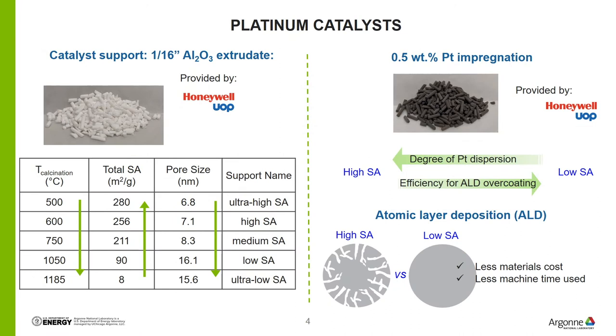This slide shows how the catalyst support looks like. The catalyst support here, which is used to support Pt nanoparticles, is a 1/16-inch diameter aluminum oxide extrudate. The same extrudates were calcined under 5 different temperatures to tune the surface area and pore size. From the table, we can see with the increase of the calcination temperature, the total surface area decreased from 280 to 8 square meters per gram, and the pore size increased from 7 to 16 nanometers. We named those supports as ultra-high, high, medium, low, and ultra-low surface area support.